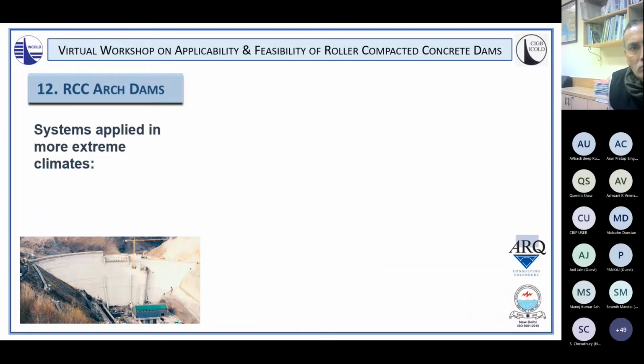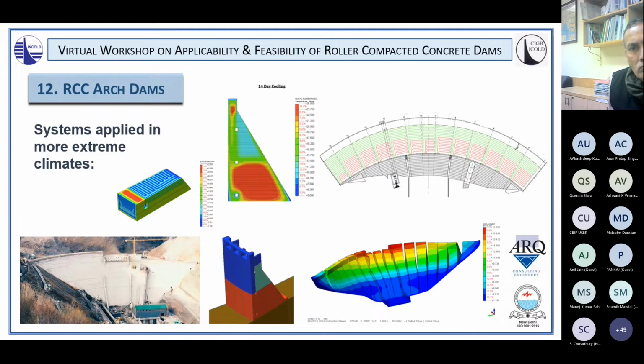On the other hand, in more extreme climates, systems have been used where part of the dam has been pre-cooled, and to take advantage of the low stress relaxation creep effects that I've been talking about earlier. And this has meant that some limited pre-cooling and grouting has then allowed the structure to subsequently tighten itself over time. So usually what happens with an arch dam is it's grouted and it may need re-grouting as it loses some of its temperature. In fact, what has been done on these dams is that they've been grouted in a manner which allows the structure to tighten further during subsequent cooling, which has been very beneficial.